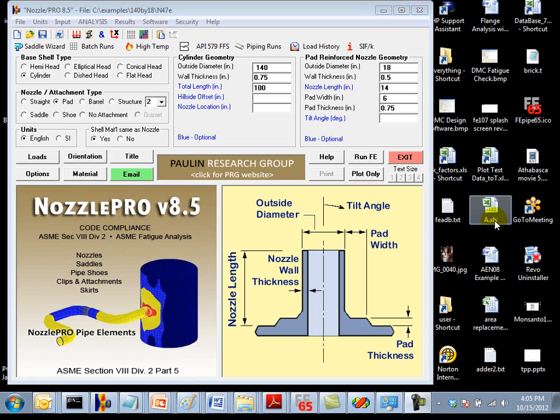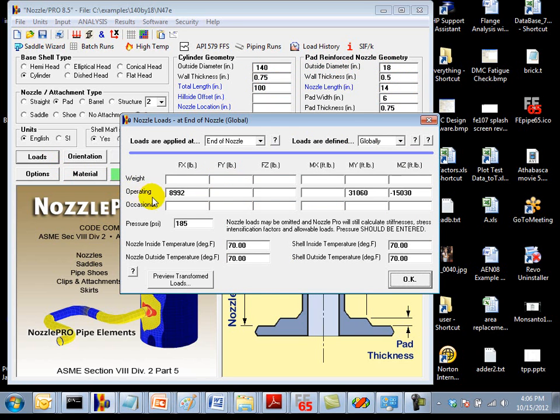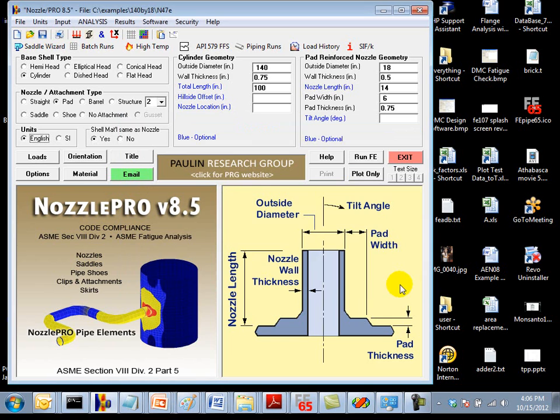The vessel has a 140-inch diameter with a 3/4-inch wall thickness. The nozzle is 18 inches in diameter with a 1/2-inch wall thickness. And there's a 6-inch wide, 3/4-inch thick repad on the 18-inch nozzle. Forces are applied in the axial direction. Moments are applied in the circumferential and the longitudinal directions. And there's a 185 psi pressure in the vessel.